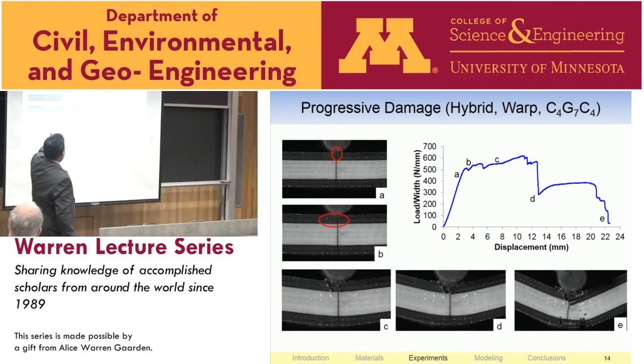So here's another picture showing what I just said, in a much broader, more, shall we say, ductile behavior that you get from these brittle materials. By designing the microstructure, you see the failure starting on the top there, compression. That's because the carbon's on the outside and it propagates. This is a thick structure.